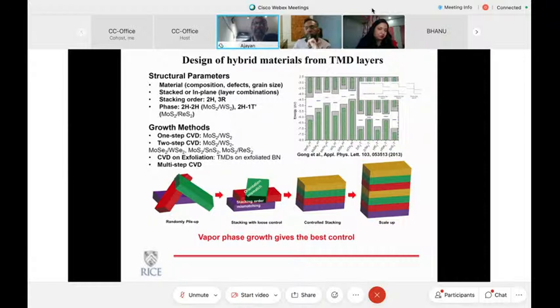But at the same time, when you start to stack these layers of different compositions, there are multiple challenges, especially if you're focusing on transition metal dichalcogenides. One of the issues is that these materials exist in both semiconducting and metallic states. So a layer of molybdenum sulfide, depending on how exactly the chalcogen atoms are sitting on top of each other in a single unit, can be either a 2H phase, which is a semiconductor, or a 1T prime phase, which is metallic. A slight change in structure, but pretty much the same composition, same lattice parameter. So first of all, if you want to control the stacking, you have to control the phase that is formed during growth. So that's a challenge.